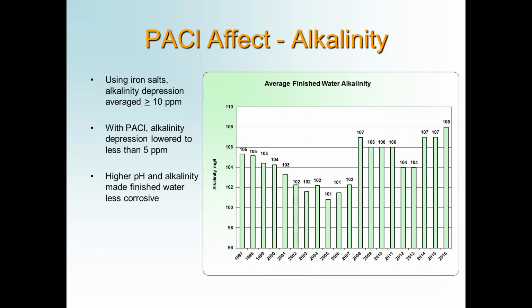The other thing that happens when you treat the water from Lake Michigan: the alkalinity of Lake Michigan is about 110 parts per million. Through the treatment process, we would typically depress the alkalinity by about 10 parts per million, especially when we were using the iron salts. When we switched over to the polyaluminum chloride, there was less alkalinity depression, so our alkalinity leaving the plant was raised by about 5 parts per million. So this switchover in coagulant, not even looking at water quality, but wanting to reduce the fouling rates in our membrane plant, resulted in a less corrosive water.